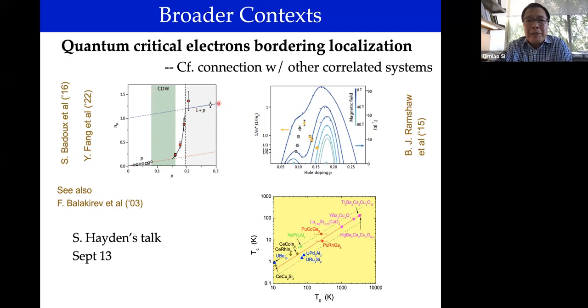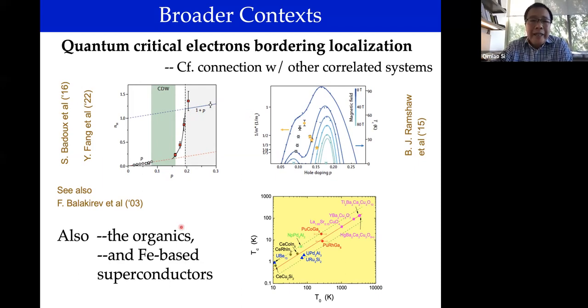Perhaps, at least in the broad-stroke sense, there's some connection to be made that this delocalization-localization feature associated with Kondo destruction in these heavy fermion systems may also be relevant to some extent for the cuprates. And the organics have, from Hall measurements, also shown features like this. And the iron-based chalcogenide superconductors, FeTeSe, Ming Yi's group has done a systematic analysis of FeTeSe and provides some evidence for a large Fermi surface reconstruction across that series.